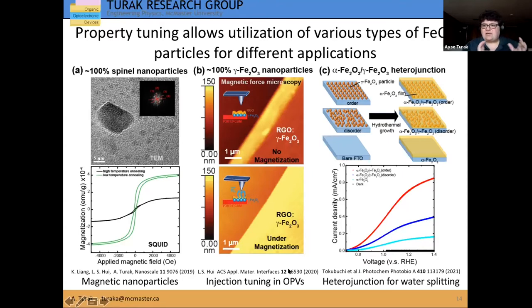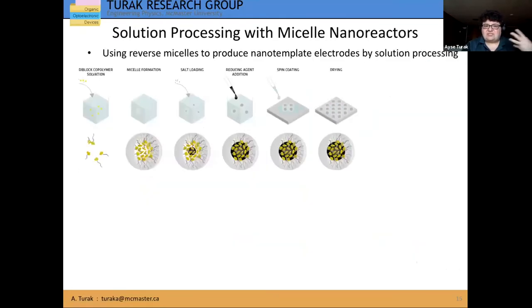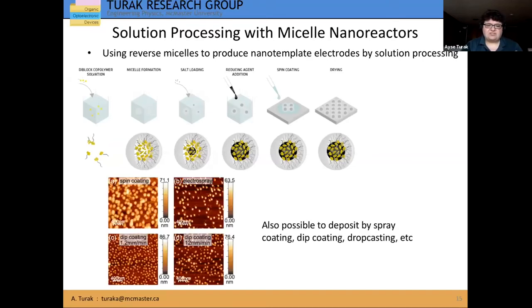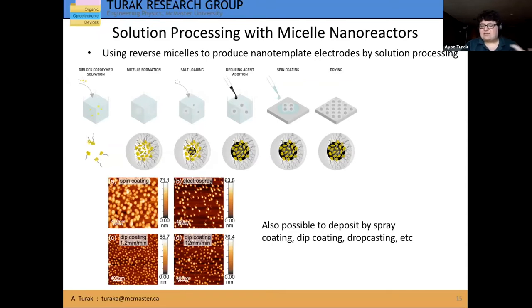Being able to tune the behavior and understanding what the structure is allows us to utilize tailor-made, bespoke nanoparticles for applications. Beyond the ability to do this sort of tuning, we can also deposit this material on various surfaces. A very simple way is to just spin coat the particles on the surface and allow nature to form a nice hexagonal array. But this approach is amenable to a wide variety of deposition techniques, and it's possible to get similar particles with similar size and similar polydispersity index using spray coating, dip coatings, drop casting, shear coating, and doctor blading — all these different approaches are accessible because it's coming from solution.